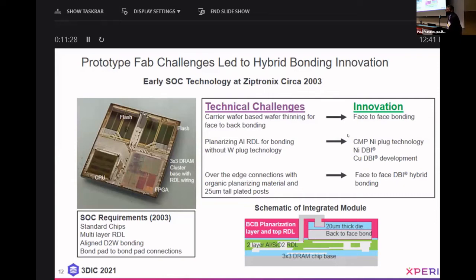First of all, thinning these die for face-to-back bonding was a very cumbersome process involving a direct bond to a carrier wafer and then back grinding and thinning, and the die had to be made 20 microns thick and then bonded and the carrier material removed. So there was a lot of work in that, and face-to-face bonding would have been much better. We had trouble with making a planar aluminum RDL at this point, because we didn't have any tungsten plug technology. So what we did to try to remedy that is we came up with a nickel plug process using CMP. And what we found was that when we polished that, it made a very flat bondable surface. And so that's really how nickel DBI was born.